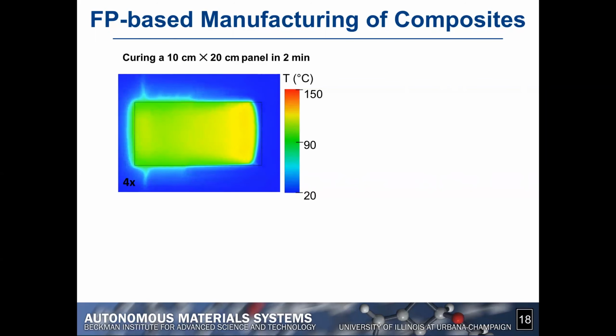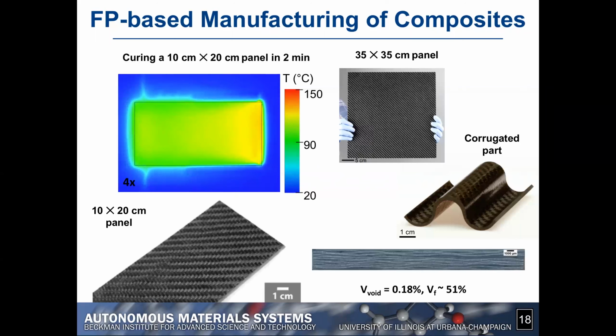And we can make various types of panels, and here is a slightly bigger panel that was made. We can also make corrugated parts. And if you look at the quality of the composite that we can make for this particular system, we can see that this is a pretty good quality. The void volume fraction is less than 0.2%. For this particular technique, we managed to make fiber volume fraction of the order of about 50%. We've since then, using a certain compaction type of approach, managed to make volume fractions that are higher than this, in excess of 60–65%.